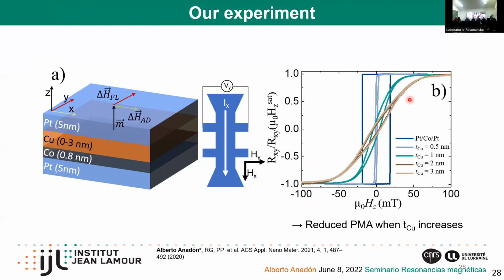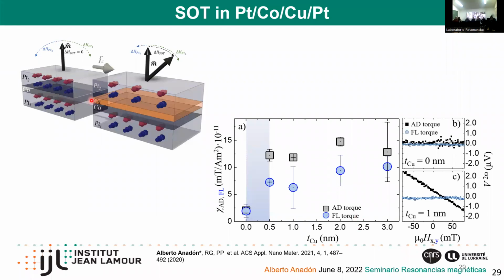So as we introduce this copper interlayer, we can already see that the perpendicular magnetic anisotropy of our system is reduced. So from the platinum cobalt platinum with no copper, we are seeing that the loop is tilting, and this is due to the reduction of the perpendicular magnetic anisotropy. And the experiment is to study how this copper interface affects our spin orbit torque. So in principle, if our copper is completely transparent and the interfaces of copper play no role in the spin orbit torque, we should see a constant, almost zero spin orbit torque, since the torque coming from the platinum on the bottom and top should normally compensate, since the thickness is similar. And copper is almost transparent in terms of spin current. Spin diffusion length is very high. So any effect that we observe here should be related to the interfaces with copper.